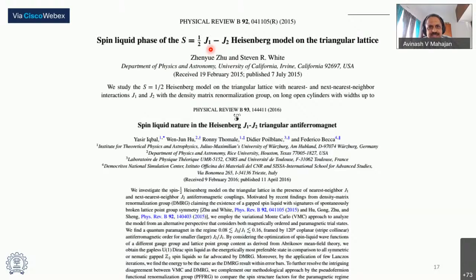There is another possibility of a J1, J2 Heisenberg model. So J2 is the next nearest neighbor. This is another one by Yasir Iqbal and people, where again they're looking at a J1, J2 triangular antiferromagnet. So presence of the nearest neighbor as well as the next nearest neighbor in the otherwise uniform chain. And in both these, they expect some spin liquid behavior in some parameter space of J2 by J1. So, it's quite possible that you have other interactions present in this system, which go beyond the simple nearest neighbor J. And that drives the spin liquid behavior.